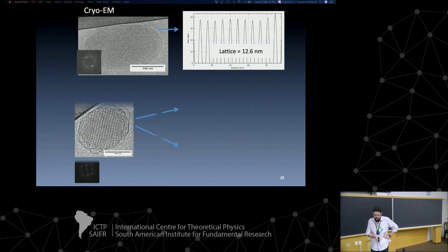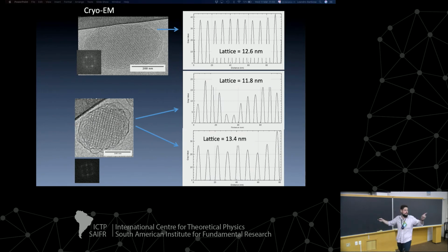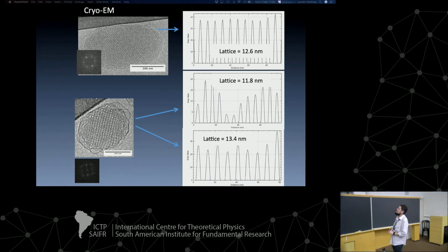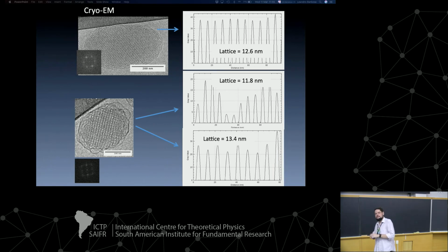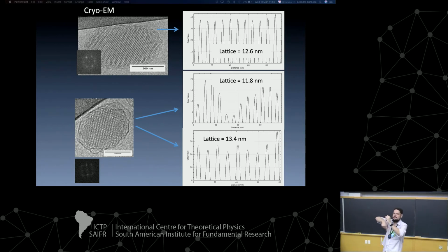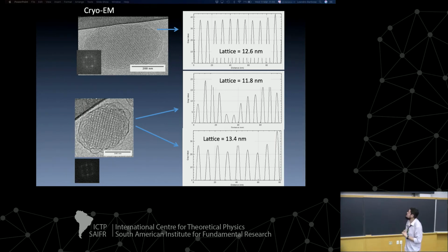Those are our results of cryo-EM. Those are images performed by Barbara. She started to work with these particular systems. This picture is quite nice because in this particular case, when we see some specific particle, please pay attention, you may infer some structure generally from your system. You see that here we have this water tube, we have this kind of globby stuff over here, which is what we believe is the polymer. So in that conformation, we believe that we have the inner cubic structure of our nanoparticle, and the outside region is composed of the amphipathic polymer that prevents these nanoparticles from self-assembling and aggregating.